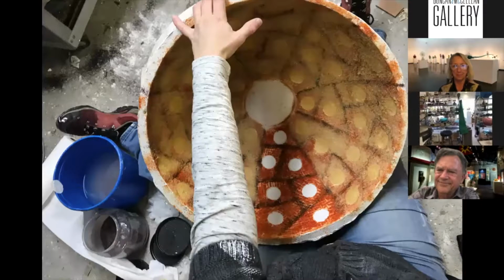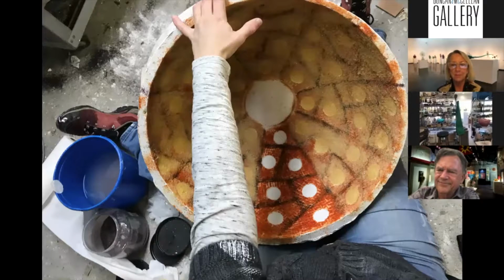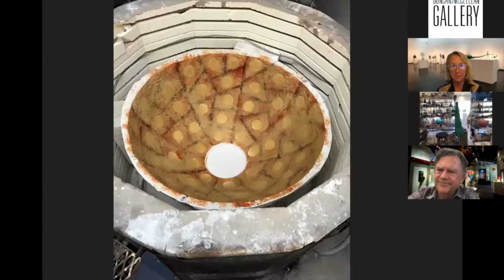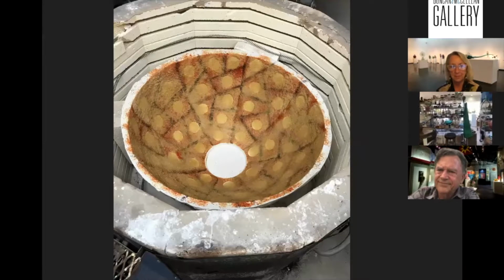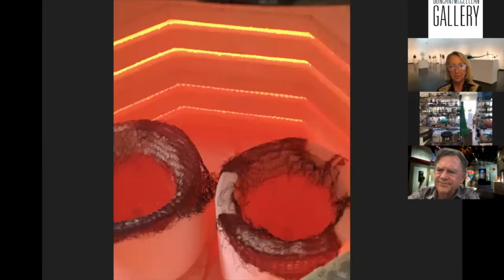That's me on the floor with a giant mold, and I do the colors in layers. I usually do at least 4 colors in a piece. So each layer is sifted in with a tablespoon. It takes hours, and then it goes into a kiln and gets fired. It's in the kiln for about 3 days. When it comes up, I have to watch it really closely so it doesn't slump.